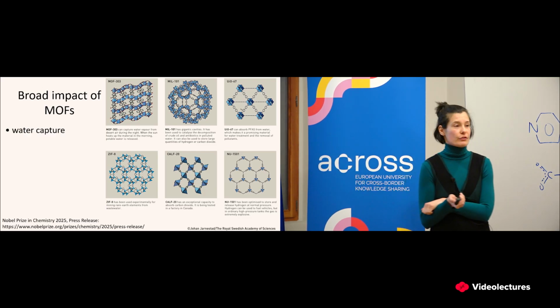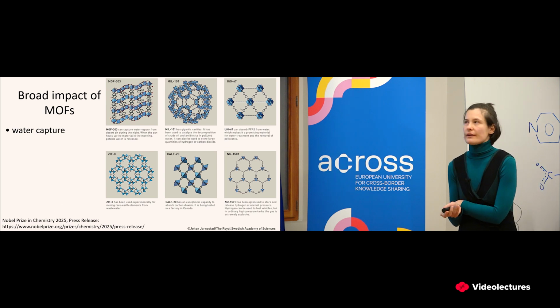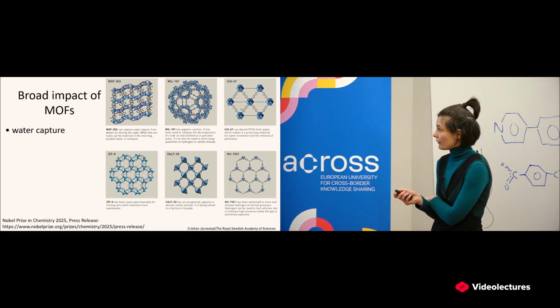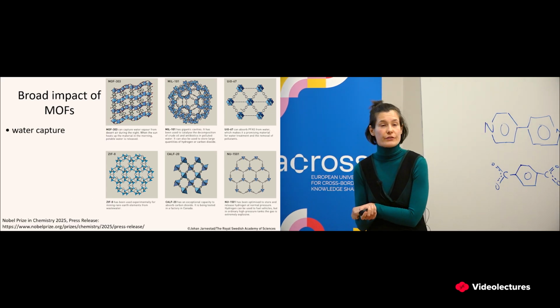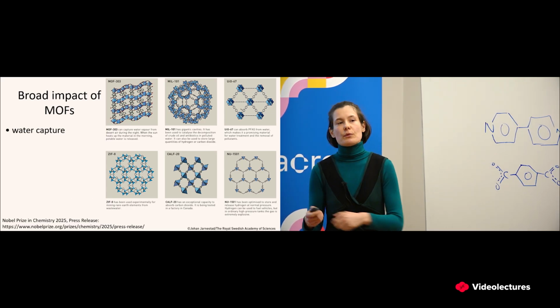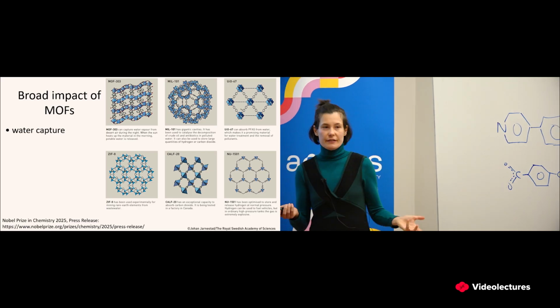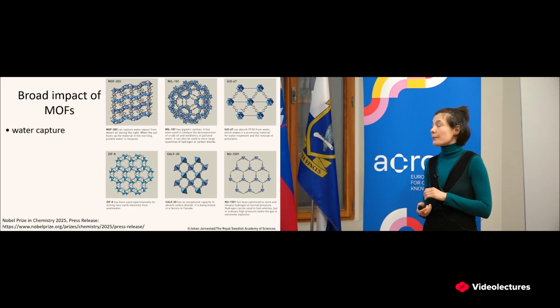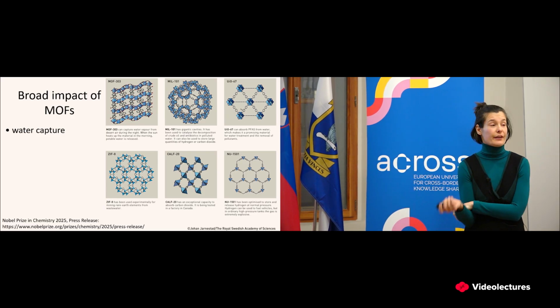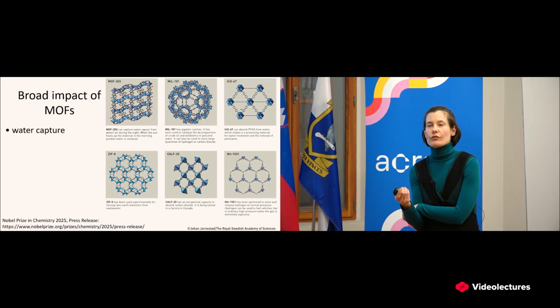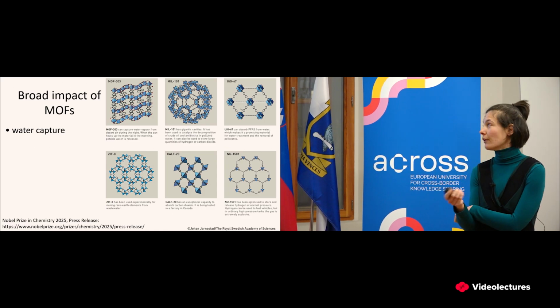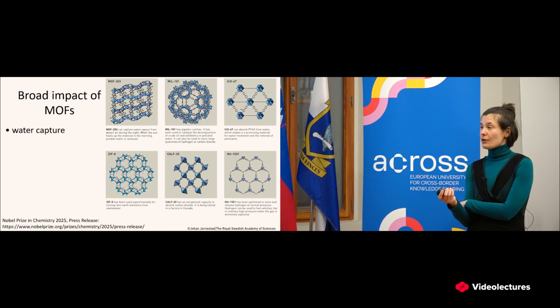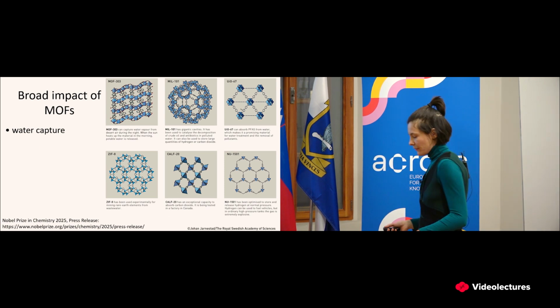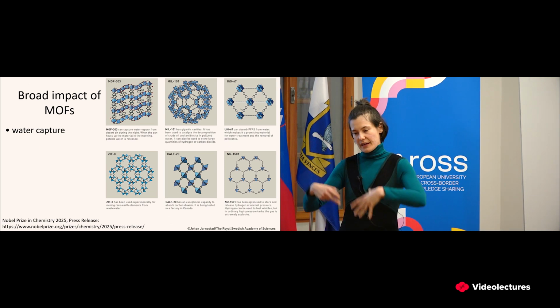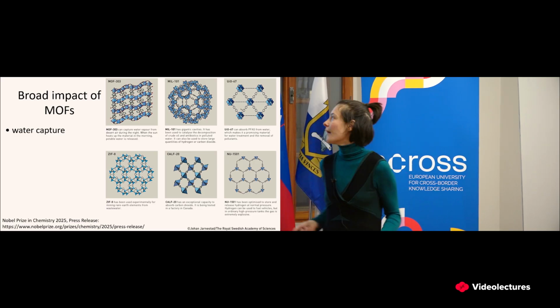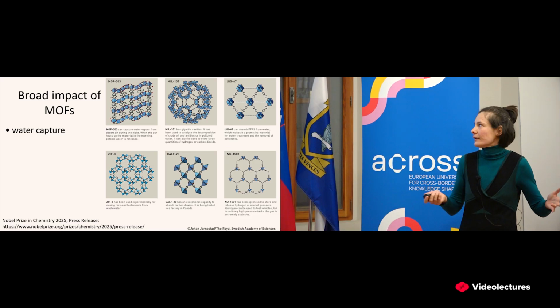So here we have examples of 6 MOFs that were each used for a different purpose. For example, this material was used to capture water in the desert at night, and then when the sun comes out during the day, you can release these water molecules. Now, why does this work? Because the organic linker in this particular MOF-303 can form hydrogen bonds with water. So it's a pyrazole molecule that can bind water molecules, and there is also this cooperative binding mechanism, so that once the first water molecule binds, the binding of the second one becomes easier, and so on. And that's why the water uptake is significant.